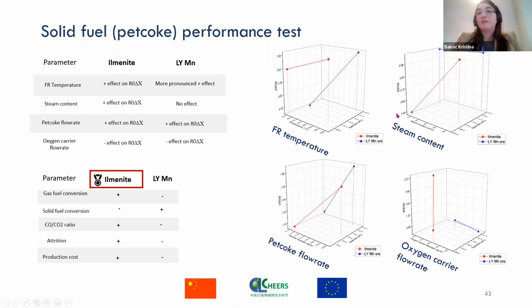In the case of the steam content in the fluidization gases, steam content seems to have a much more pronounced effect when we operate with ilmenite, while during the operation with LYMN, the effect of the steam content on the overall values of oxygen transfer capacity seems to be quite negligible. As for the petcoke flow rate, as would be expected, if we provide more fuel, there is more exchange of oxygen. So we achieve higher values of R0 delta X in both cases. However, for the oxygen carrier flow rate, we find that if we push for higher values of oxygen carrier flow rates during the operation, this will actually reduce the capacity for oxygen transfer. And it makes sense since it would probably allow for lower contacting between the oxygen carrier and the actual fuel. So this is something that should be avoided normally during the operation.